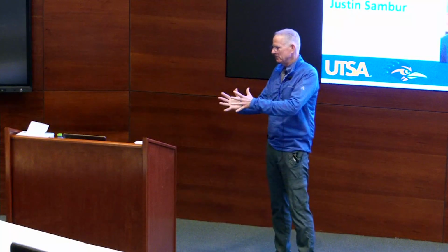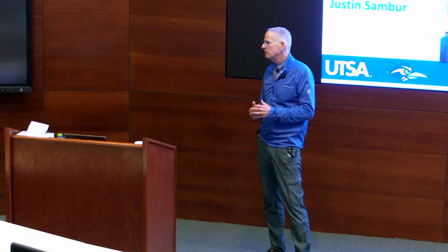I think it's pretty likely it's the aggregation. It is a different excited state. It's excimer-like, meaning that it's aggregated before you excite it, as opposed to coming together in the excited state. But it's a sulfonated polymer, so protonation is not likely, because you'd have to go to pretty low pH to change the protonation state of that sulfonate group. So I think our proposal is a good one.